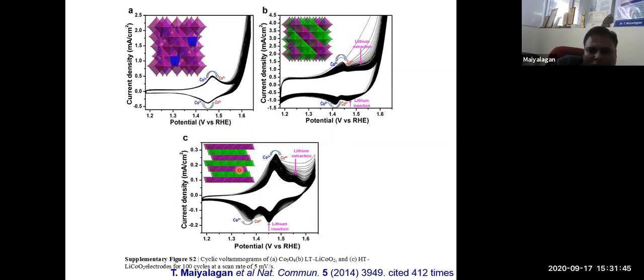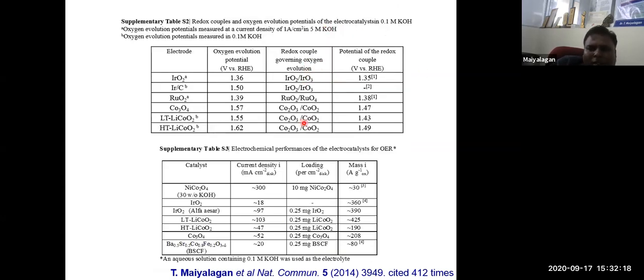During charging and discharging, lithium insertion takes place very fast. Here, spinel structure. That's why this material has been used in lithium ion batteries, because when you're charging and discharging, lithium goes in and comes out in this one. So that is why people used this material in lithium ion batteries. And we have tried this material for this oxygen evolution. You can see that the oxygen evolution reaction takes place at low onset potential, and this material is giving better performance. As I said, the redox couple helps in the oxygen evolution reaction, oxygen production,